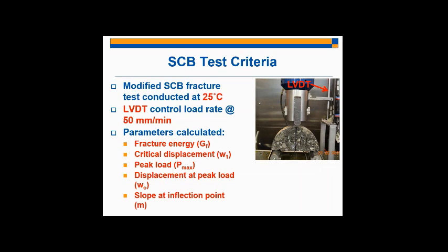But we've shifted the temperature to 25 degrees Celsius, and we've shifted the displacement control from the bottom horizontal displacement of the specimen, which we call the CMOD, to basically the LVDT. So the test is now controlled by the linear variable displacement transducer, shown to the right of the figure here. And it's basically just a vertical displacement that controls the displacement rate of the test.